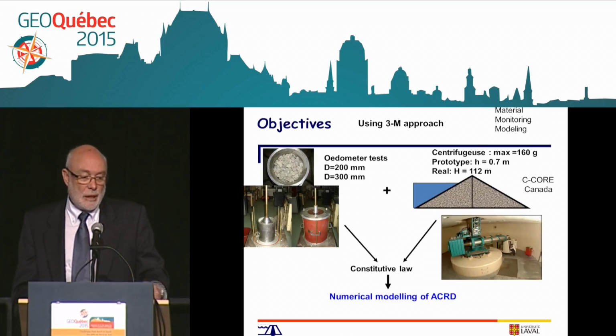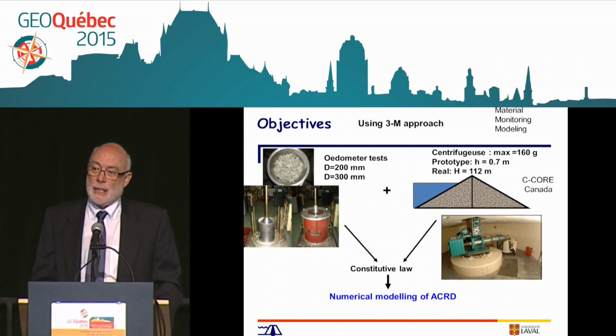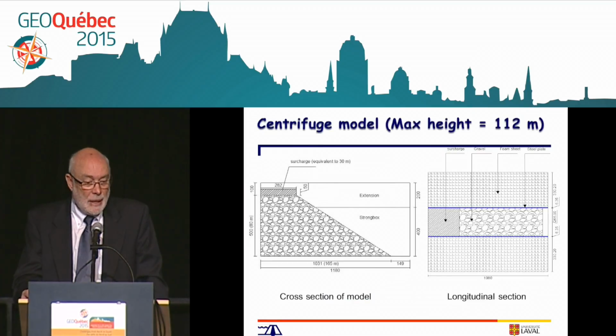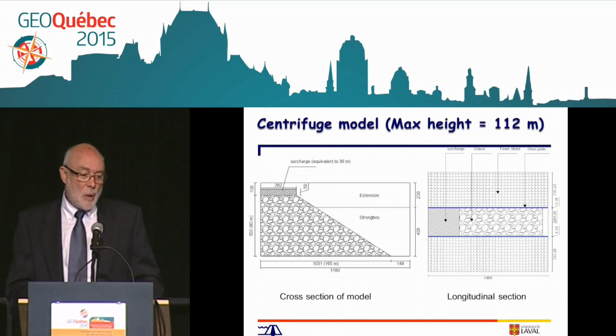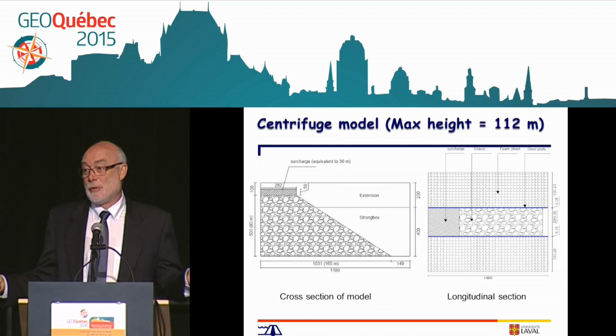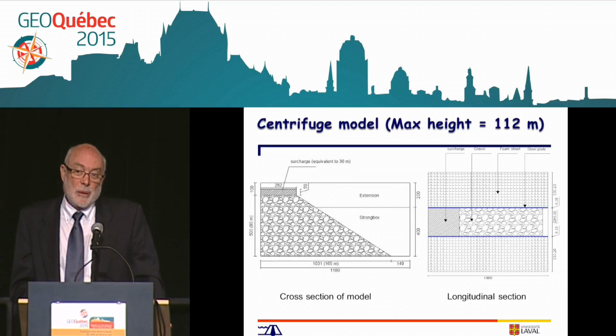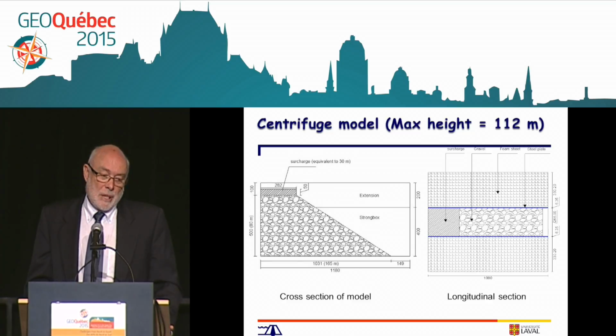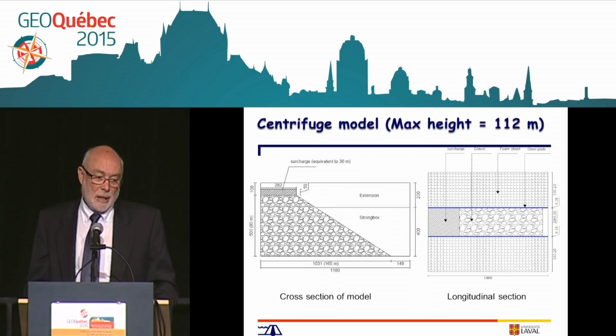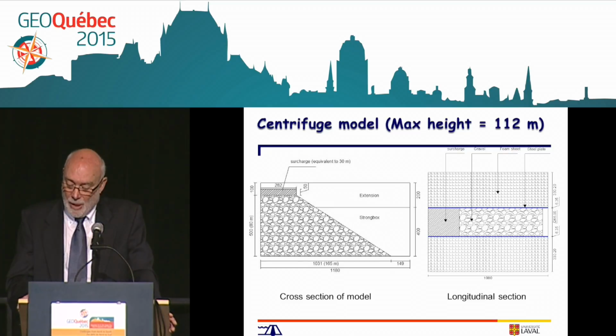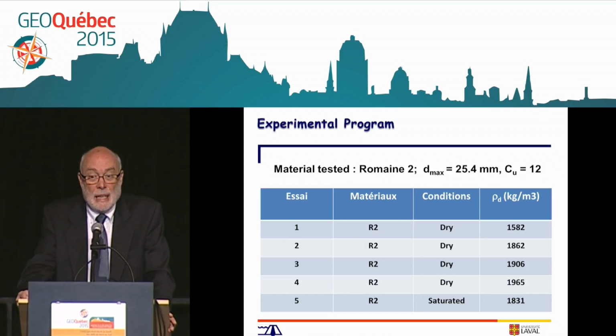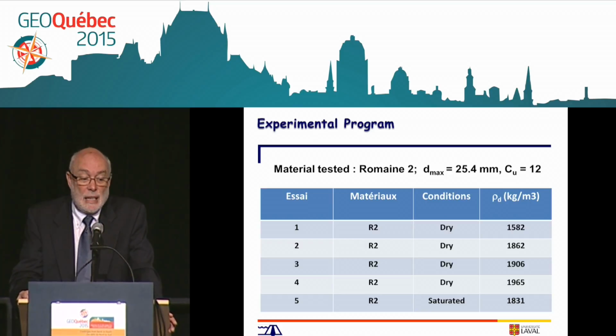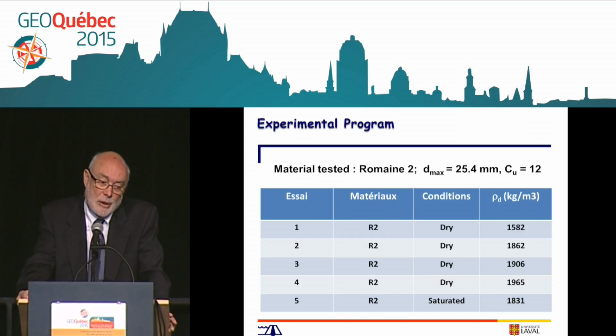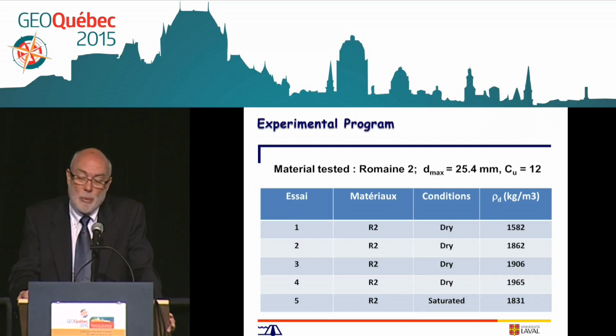The objective is to use a centrifuge to see if there is a difference between a 2D loading system compared to a 1D in the oedometer. And we did two types of tests, the one on half a structure because of the size of the box. The box only allows us to put about a 50 centimeter high structure. So by taking half of it, we were able to model with a surcharge the maximum height of Romaine 2. We then did five tests, four at different densities, one in a dry condition and one in saturated conditions. And we used Romaine 2 material that was 1 inch maximum size, 25 millimeters, with a coefficient of uniformity of 12.